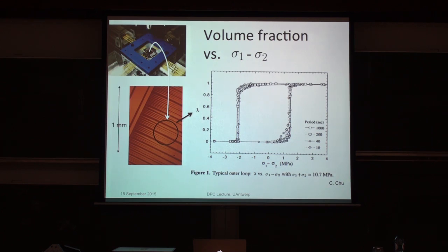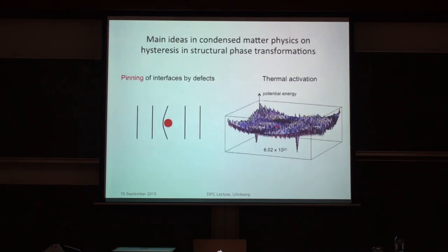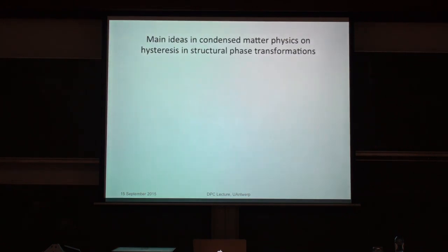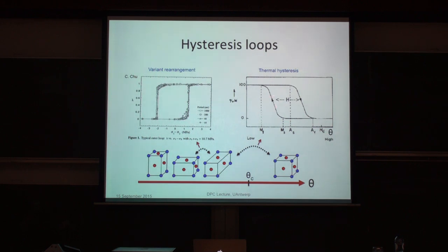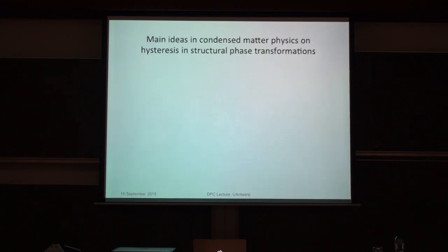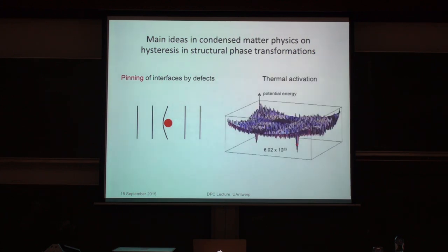We do have rate effects. If we go back to here, in the case of transforming between one phase and another, this can be slightly changed by rate, by doing different rates, but it does not shrink to zero when you make the rate go to zero. So hysteresis in phase transformations is not caused by some kind of viscosity like in fluid mechanics; a viscoelastic or viscous effect is not the right effect for phase transformations.